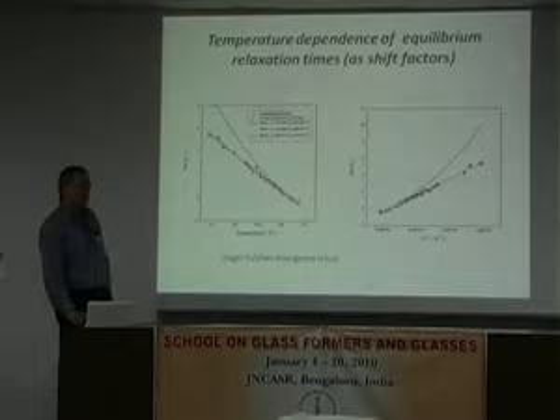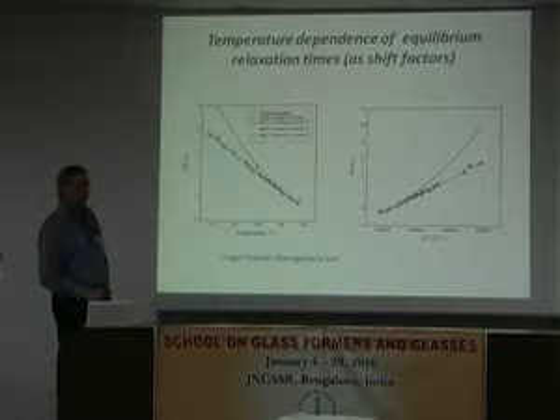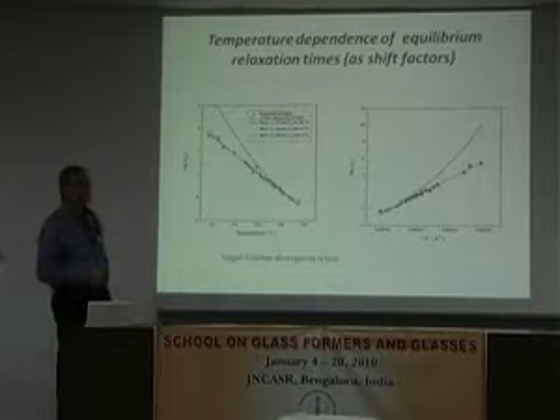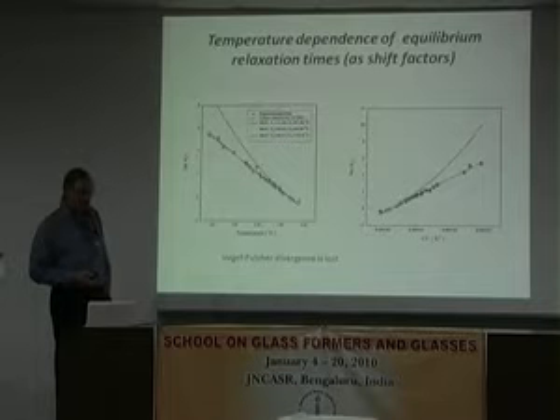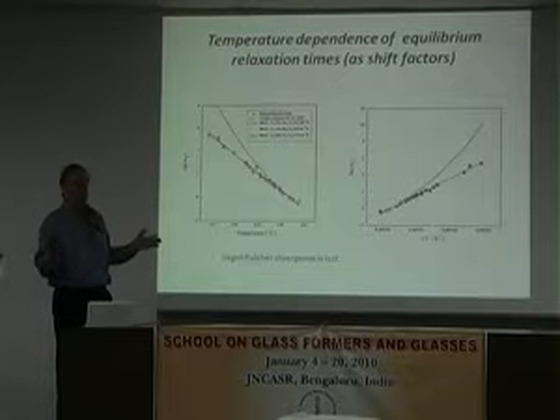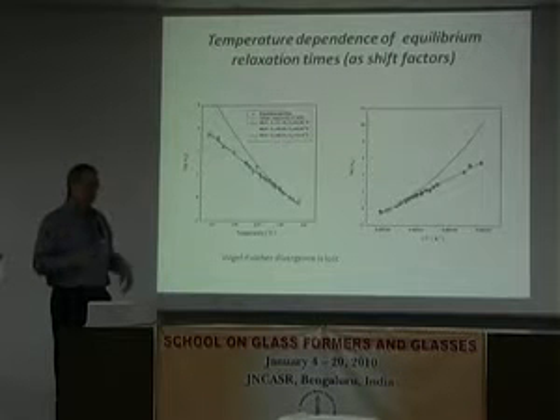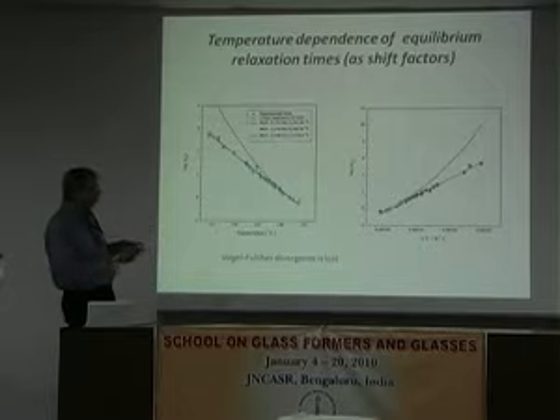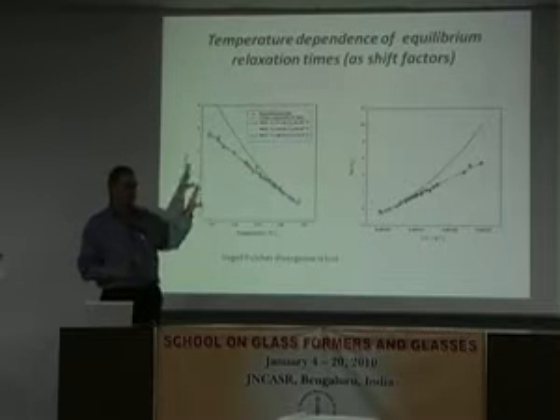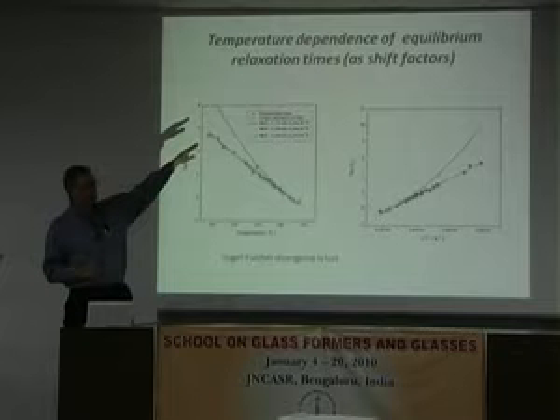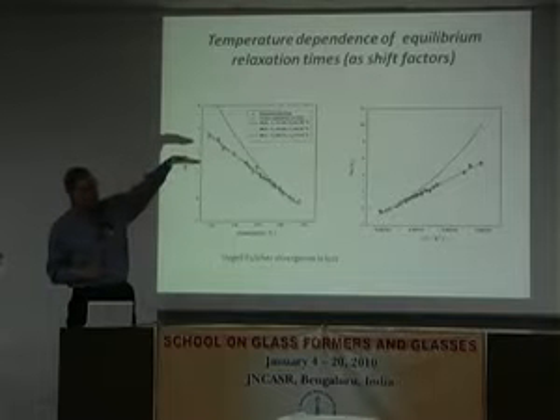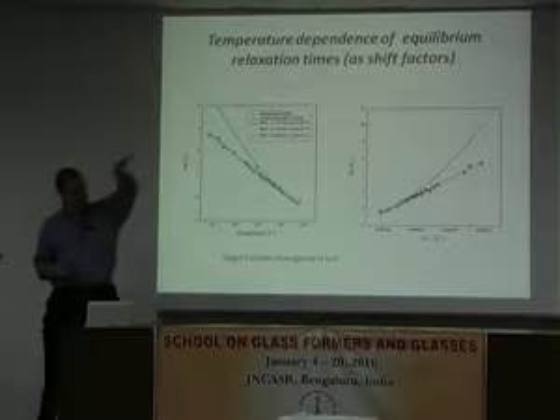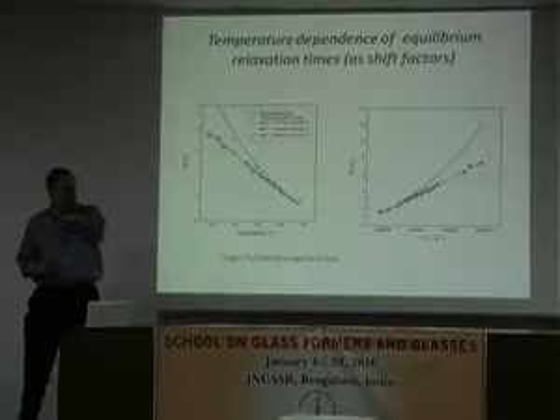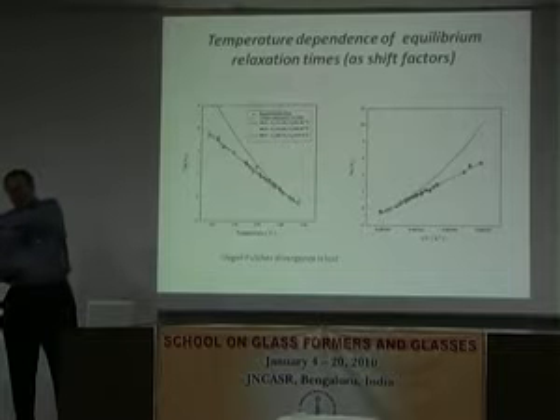So is this simply telling me that there is a deviation from Vogel-Fulcher? Yeah. But in principle, you can also see this above the glass transition temperature. In some instances, J.B. Dyer has just written a big article saying we see this everywhere above the glass transition. So really, my comment on this is that, depending on the material, if you did a Stickel plot, you'd have an Arrhenius, some sort of Vogel-Fulcher-like behavior, and then a higher temperature Arrhenius and maybe some other things.